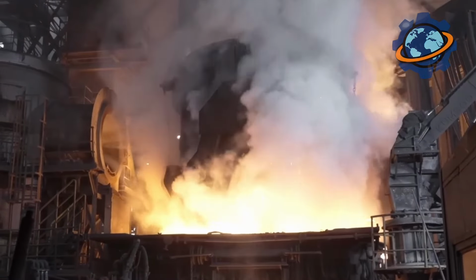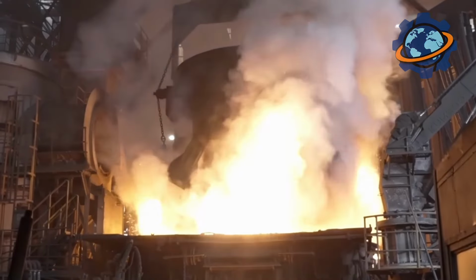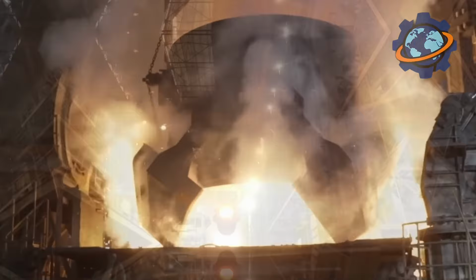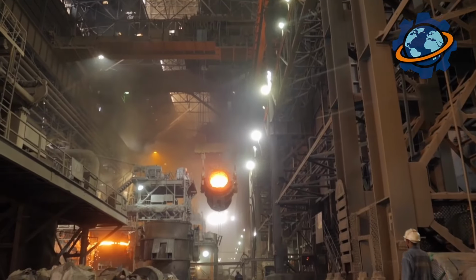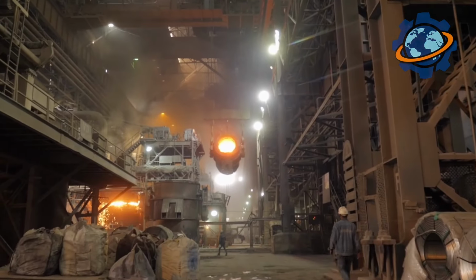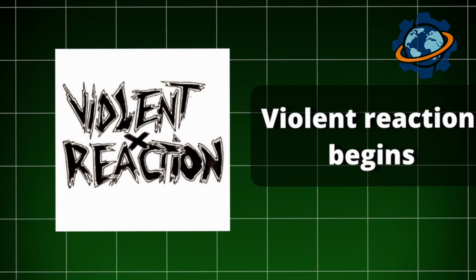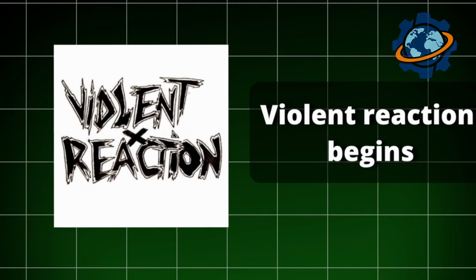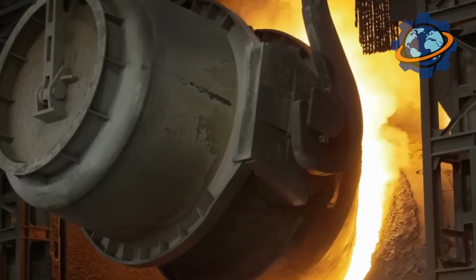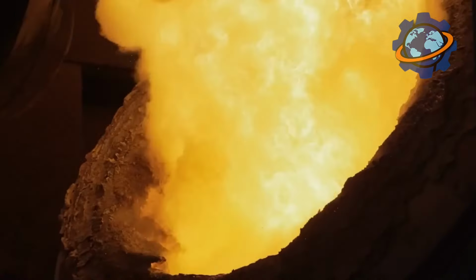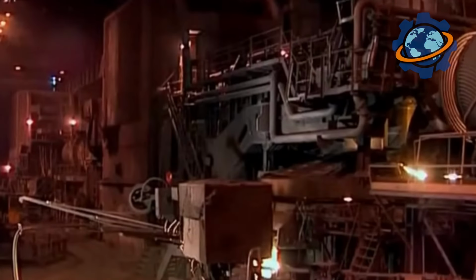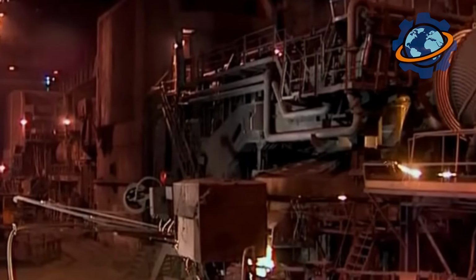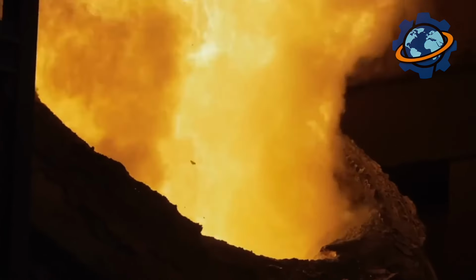The converter returns to vertical position. An oxygen lance, a tube 20 inches in diameter, lowers from above. Oxygen flow begins. A jet of pure oxygen at 150 pounds per square inch pressure strikes the molten metal. Violent reaction begins. Oxygen oxidizes carbon, silicon, manganese, impurities in pig iron. These exothermic reactions release enormous heat. Temperature rockets to 3,200 degrees Fahrenheit.